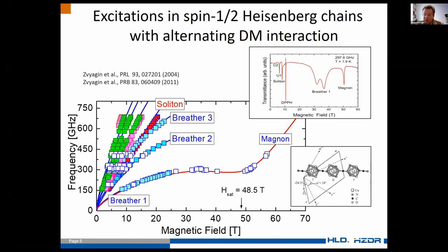And of course, it's very interesting to see what's going to happen in high magnetic field. And this is where the high magnetic field is very necessary. So it's known for this material, this is copper pyrimidine, that at about 50 tesla, 48.5 tesla, the magnetization gets saturated. So saturation means we completely kill all the quantum fluctuation, all the quantum effects are suppressed.